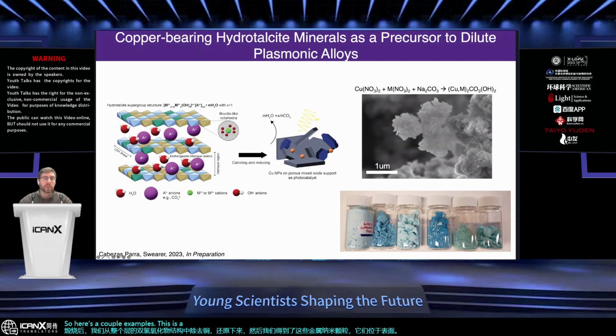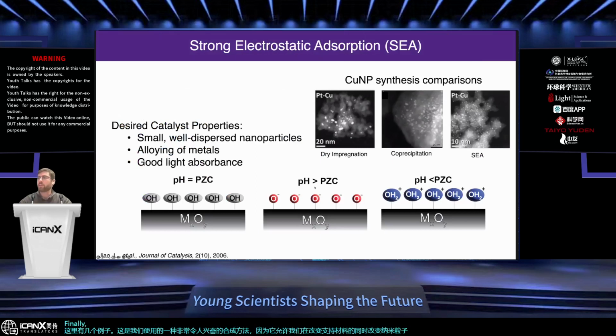This is a really exciting type of synthesis because it allows us to vary the support material while at the same time varying the nanoparticle size and distribution overall. Finally, another technique that we use quite a bit in my lab is strong electrostatic adsorption. This is great because it gives desired catalyst properties such as small, well-dispersed particles, allows for easy alloying, and allows for great light absorbance, which of course is what we're going to want in a photocatalytic system.